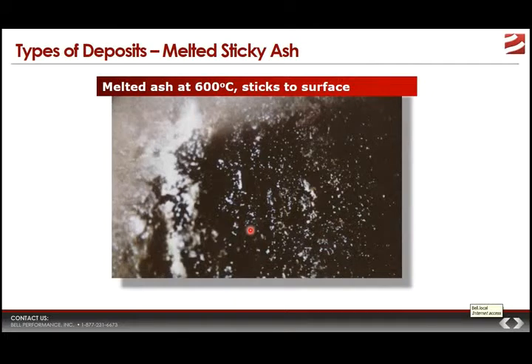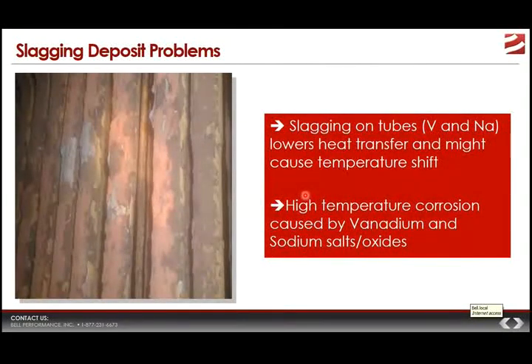That happens, you can get something that looks like this. This ash deposit has a melting point of only 600 degrees centigrade. Typically, the hotter areas of the system have temperatures higher than 600 degrees, significantly higher. And so it will tend to exist in this kind of shiny semi-liquid state that you can see here. Because it's sticky, it sticks to surfaces really well. It sticks more tenaciously to those surfaces, which makes it harder to clean off during service intervals. In other words, it increases the maintenance costs associated with cleaning these off during service intervals.